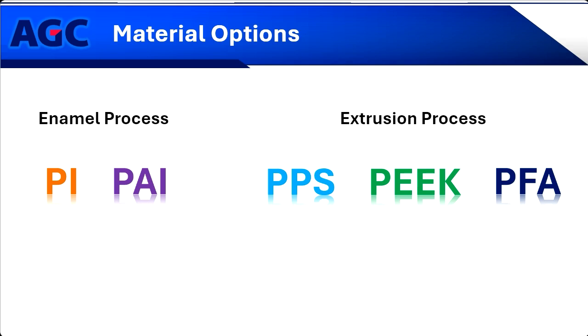So an initial advantage of these materials is the fact that they are extrusion processable. Typically, extrusion is a bit more straightforward than the enameling process. You typically do not have to do multiple passes over the wire to get a really good, consistent coating onto the wire. And you don't have to worry about any of the solvents that might be necessary for the enamel process. So I'm sure if you're on this call, you're probably aware that PEEK is really one of the materials being highlighted for this application right now as the next generation material for 800 volt and higher motors.